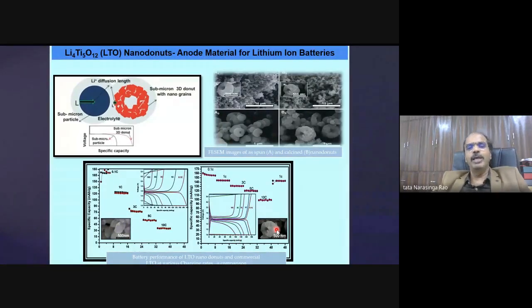And then she made these materials by electrospraying, and luckily she got a nanoparticle, but within the nanoparticle you have nanograins with a donut-shaped, like vada kind of shape. So here what happens is your electrolyte diffusion happens through all sides within that, and your charging and discharging is so fast. Now, if you see the bottom ones, when I say C rate, 0.1 C is very slow.